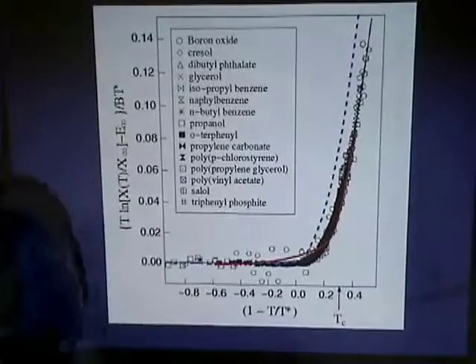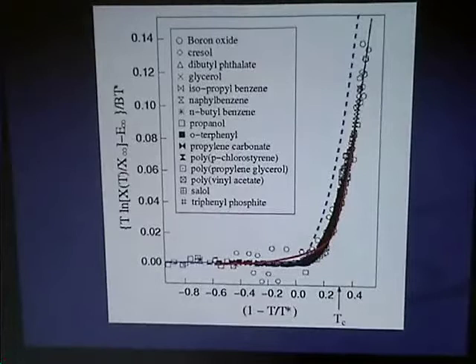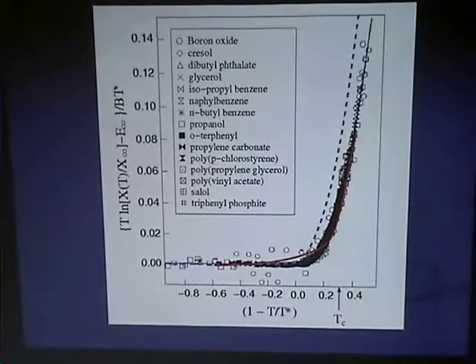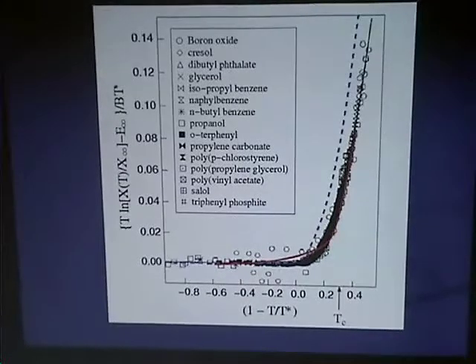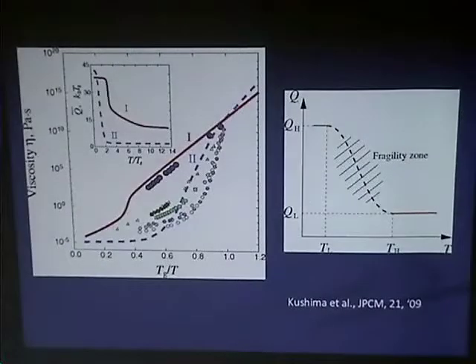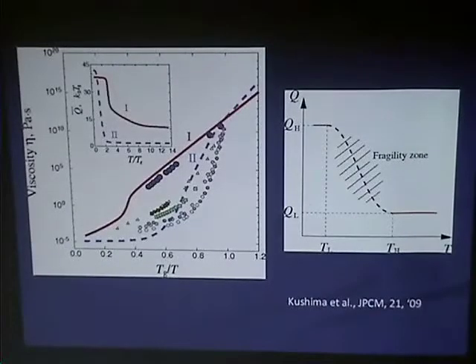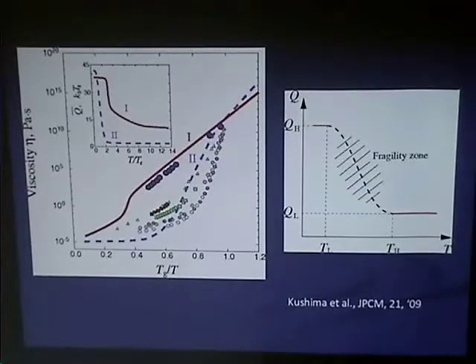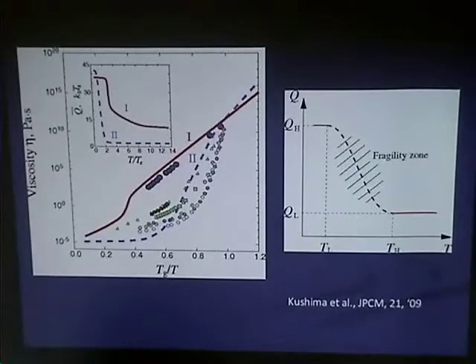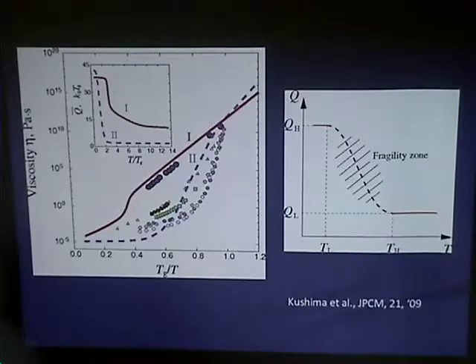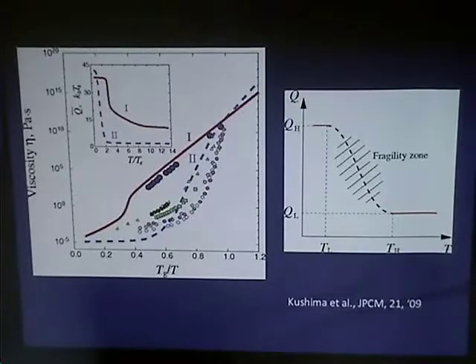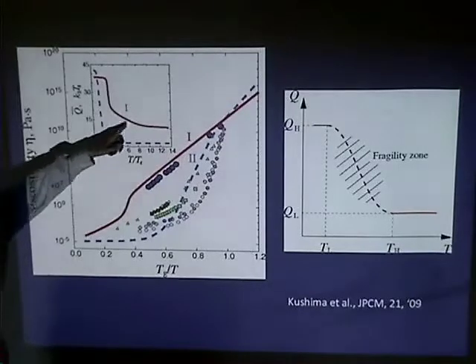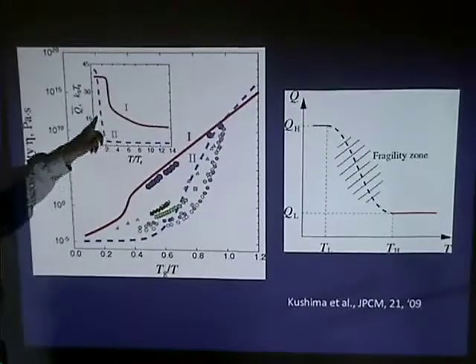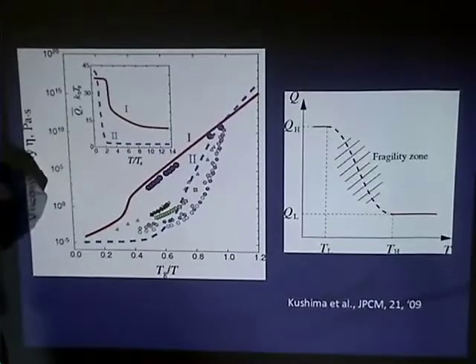There's something else going on here as well. In this plot and in the plot that you just had, all of the data are for polymers or molecular liquids, except for silica, which is different. Now, when we try to project this to metallic glasses, they are much more like silica. They're still fragile, but they're stronger than a lot of these molecular liquids. So when we look at curves 1 and 2 up there and talk about the breadth, metallic glasses are probably going to be somewhere in between. Silica is very broad, as we have said.